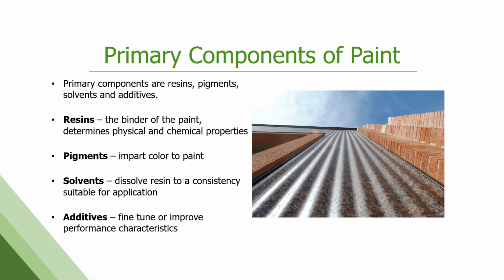Solvents. There are no solvents, like I said, in the final product. That's all burned off during the manufacturing at the coil coater, but that solvent ratio is important. We need these pigments and resins to stay in solution properly while they're being transported in the drums. It has to be a consistency that the coil coater can pump out of the drum into the coater head. Easy cleanup, and it's got to be solvents that are not terribly dangerous to either people or the environment as well. And then there's additives. We kind of joke that the additives are the magic fairy dust that paint suppliers put in their formulas, and that can be anything, from fine-tuning flow and appearance to subtly adjusting gloss. There's a wide range of additives, but they tend to be a very small component of the overall formula.